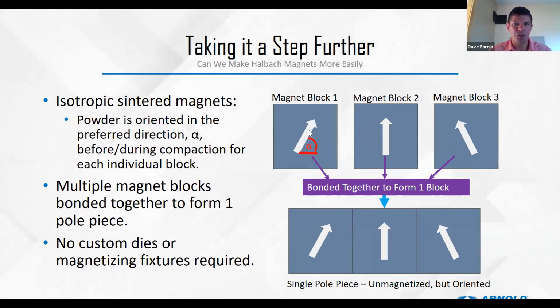If we take these individual blocks and then bond them together to form a single block, we sometimes can magnetize this as a single pole piece. So now we can bond unmagnetized blocks together, magnetize them as a single pole piece, and then make our assembly process much easier. At the same time, if we look at the tolerances, each of these magnets separately is going to have its own tolerance. Together, we would cut the magnet out, and then our tolerance would be covering those 3 magnets. So our stack up, if we're making a rotor with multiple segments, cutting the segments down by 1/3 is going to reduce that stack up tolerance.